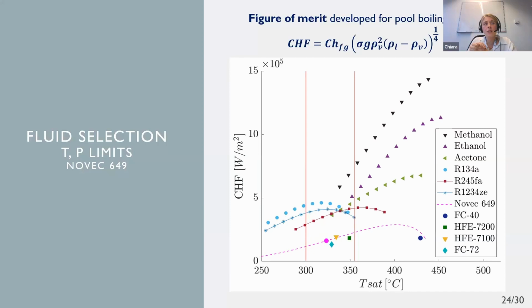And the first step was to investigate just a system running at ambient pressure, so not pressurized systems. For this reason, we decided to compare different fluids that are currently adopted in refrigerant and cooling systems by using, as a figure of merit, the critical heat flux correlation developed by Zuber. That essentially, as you can see in the equations above, is related to all the thermophysical properties of the fluid: liquid and vapor densities, surface tension and latent heat. It also depends a little bit on the liquid surface interaction through the constant C. So in the figure, we can see different fluids compared, again, comparing their nominal critical heat flux limit.